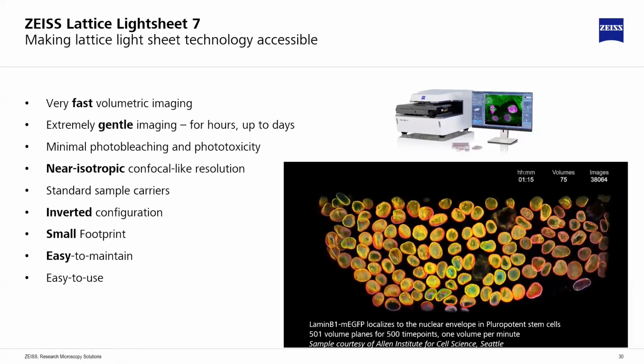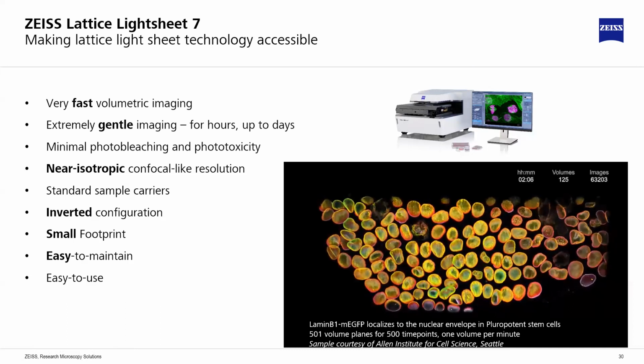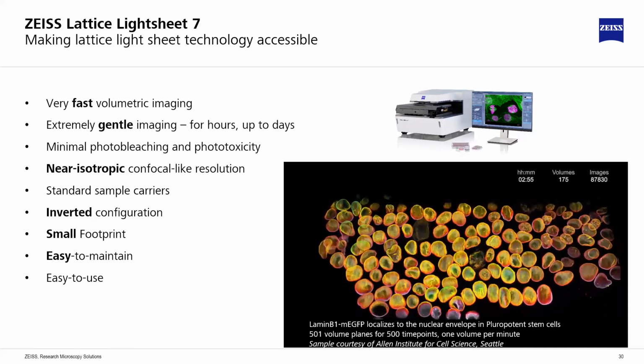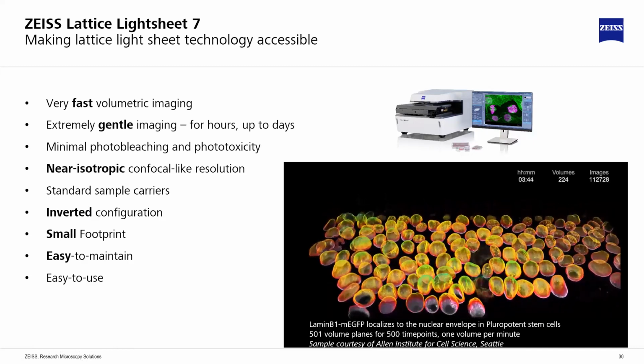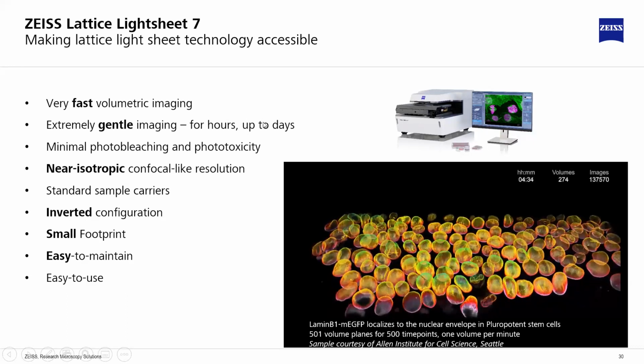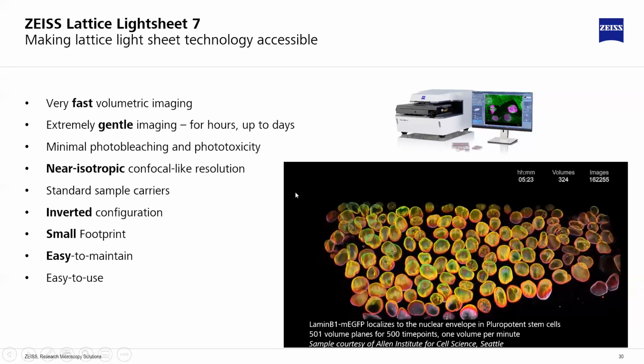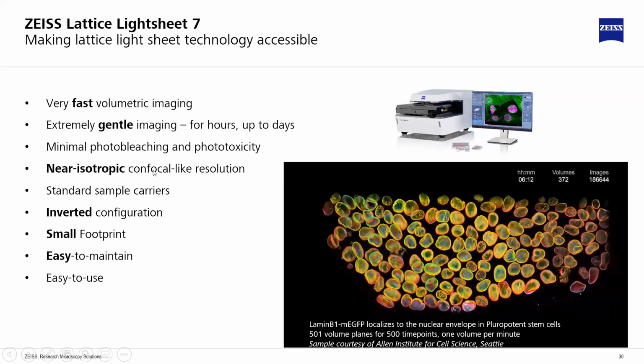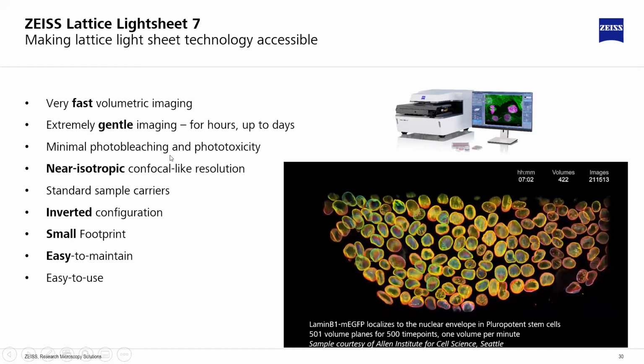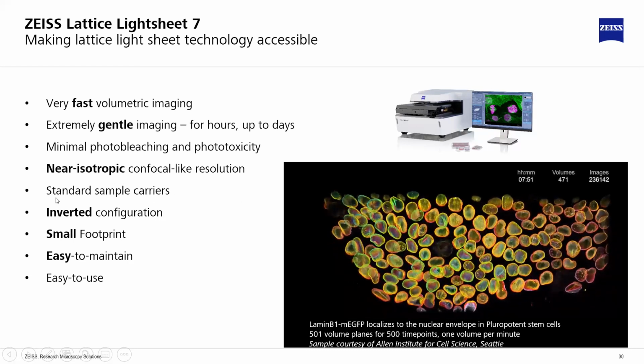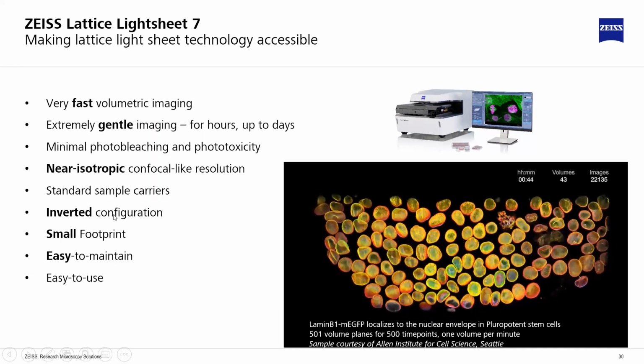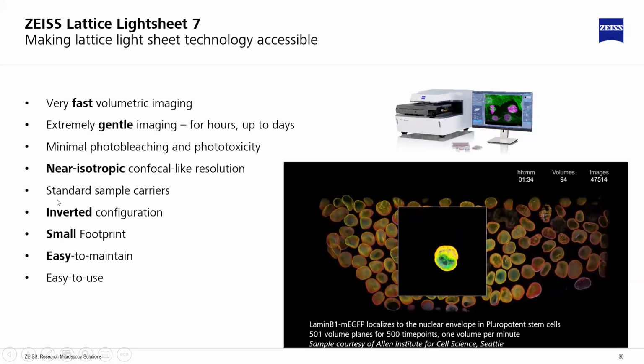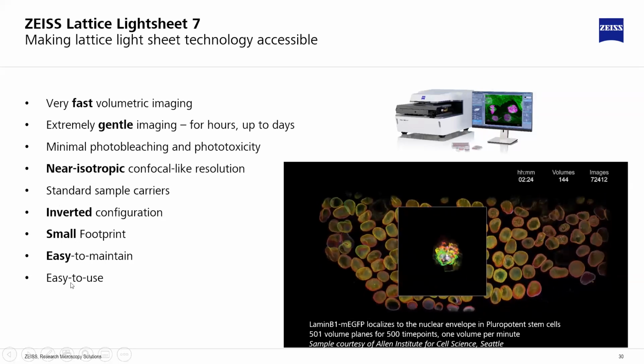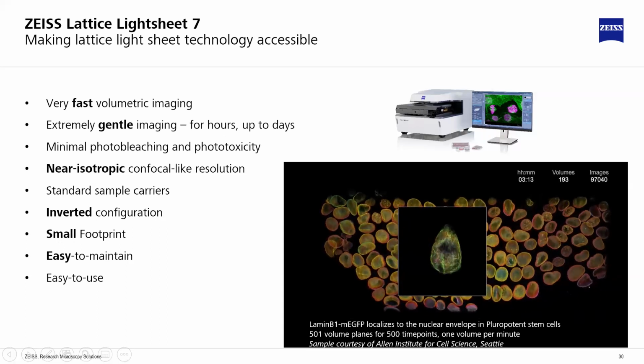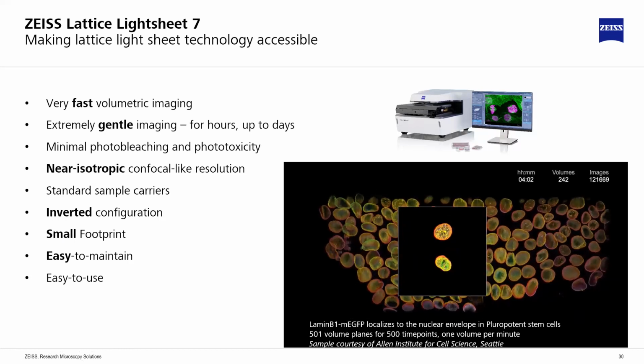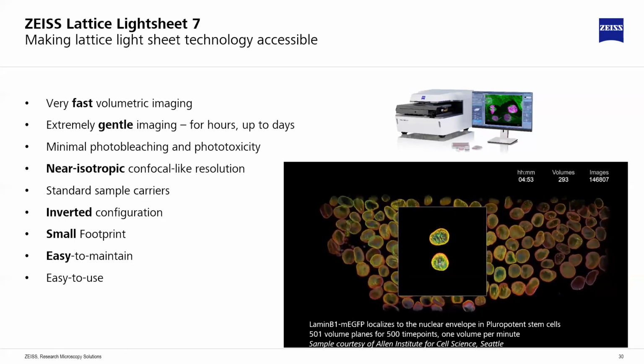The lattice light sheet 7, I think, really does provide the best solution for very fast volumetric imaging. It's very gentle. With minimal phototoxicity, you can perform time lapses for hours or up to days of continuous imaging. It provides near isotropic confocal-like resolution, as we just mentioned, the resolution capabilities of the system. And it is very simple in that it is a standard inverted configuration that can accommodate your standard sample carriers. It's a small footprint, it's easy to maintain, and it's easy to use. And I think all of these come together to make it a very powerful system for a core facility like you folks have here at Vanderbilt.